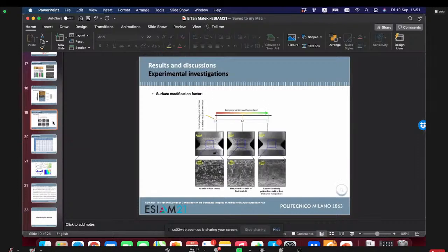Yeah, actually, we deeply analyzed the fracture surfaces in all of the treated specimens. It was found that in the as-built samples and also treated samples in the as-built state, we have some major crack initiation sites, one or two, but in the heat-treated samples, we have multiple crack initiation points from different areas of the notch root.